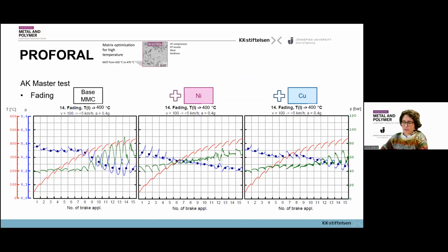If we look into fading, we end up with the same result in terms of coefficient of friction. We have the decrease towards the end at the 15th brake application. The coefficient of friction is slightly higher with the two experimental materials, but most importantly, the value of pressure that is required to obtain that coefficient of friction is much lower or with less variation compared to the reference material.